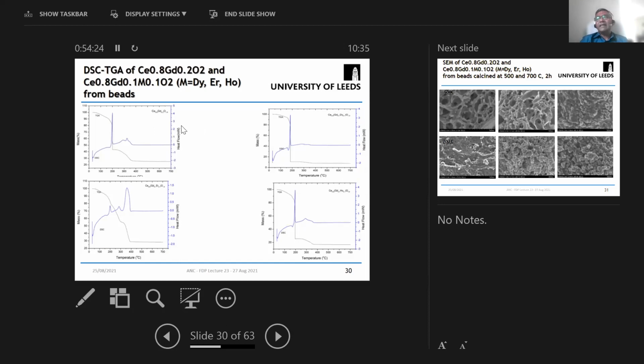So as I said before, the calcination temperature surprisingly does not change very much in spite of the change in cations that we try to ion exchange with. Whereas in the solid state, if you try to adopt a solid state method to make these nanopowders, you will need to calcine at significantly higher temperatures to form a solid solution, because you need to be able to dissolve cerium oxide into gadolinium oxide and then dysprosium oxide. So if you choose three different oxides and ball mill them together to produce the solid solution, such as CGO doped with dysprosium, erbium, or holmium, then you will require at least, I would say, 900 degrees Celsius to form a solid solution of oxides, or even higher sometimes.